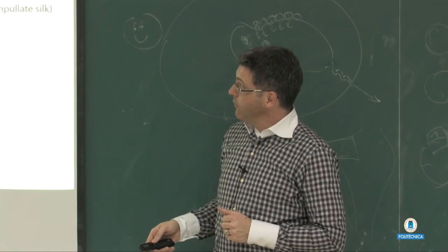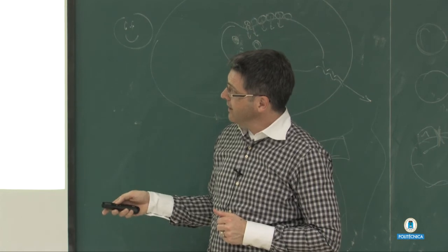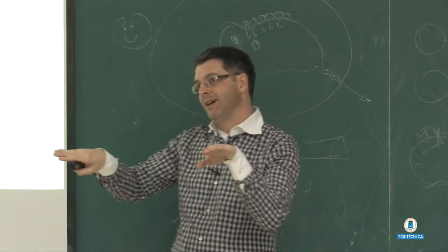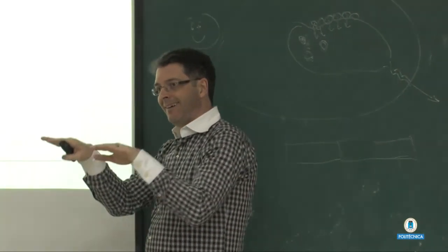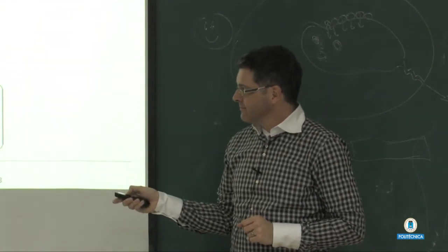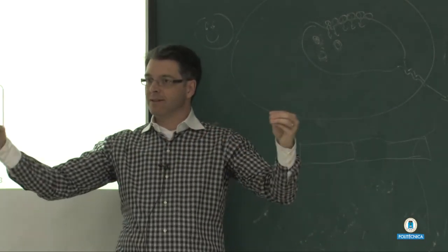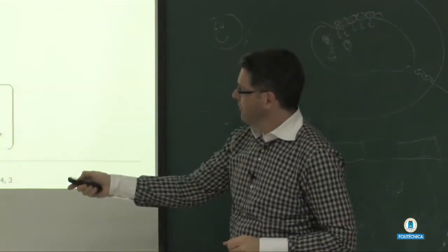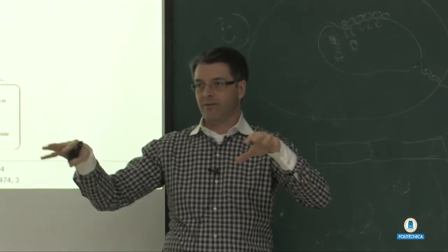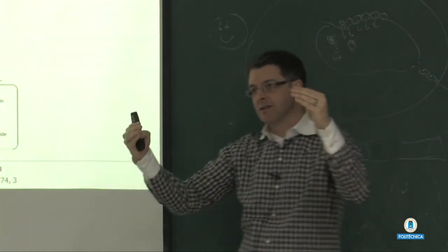And the reason why we succeeded is that by using that technique and by making this seamless cloning technique, we really could remove everything that might interfere with the stability. So in simple words, we did sort of a cleaning out of the sequence. So these are the functional sequences, and in between there is always some chunk that connects the stuff. And the chunk is also responsible for unspecific interactions.